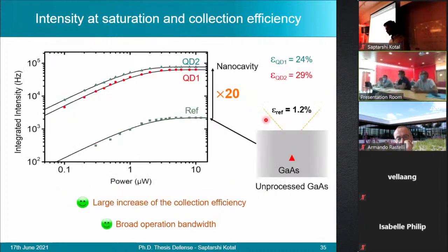exciton or a trion. To determine the source brightness, what I did was to compare the saturation intensities of QD1 and QD2 with a quantum dot that was embedded in an unprocessed gallium arsenide sample. The calculated collection efficiency of such an unprocessed sample was found to be 1.2%. And as the graph shows, we obtain almost a 20-fold increase in the saturation intensities in the nanocavity quantum dots. Additionally, despite the vastly differing wavelengths of the two quantum dots, we observe that they both saturate at roughly the same level. This is a signature of a broadband operation bandwidth of our nanocavities.